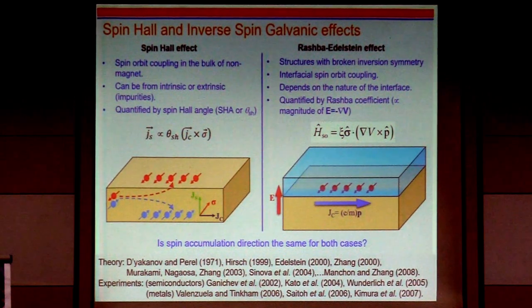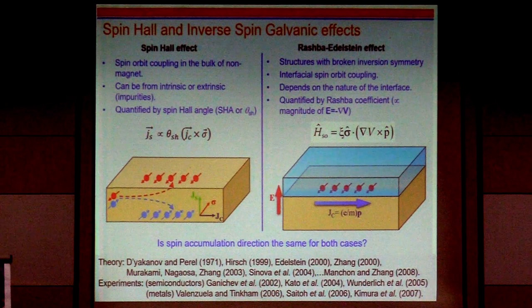But in reality, it's not very easy to distinguish. Because if you look at this case, as a starting material, what do you have when you do the experiment? You start with a substrate. So you have substrate and your material, you have an interface. If you have an interface, you have this effect coming from the interface. Now, if you look at the top, my material has another interface. If you are a theorist, you call it a vacuum interface. But in a real experiment, there's no vacuum. So it's a capping layer or air interface. Another interface will give you this effect. So in reality, it's not easy to distinguish. But referees always ask us to distinguish which one is dominant in your case.